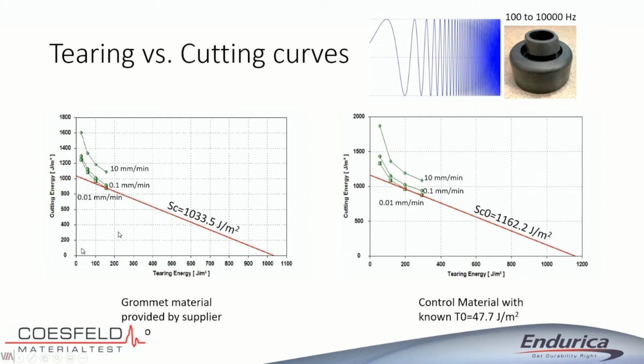Now, what you're looking at is a plot that has two axes. The x-axis is the tearing energy that acts on the crack that is due to straining of the material. So we're using a planar tension specimen. If you're familiar with crack growth measurements, same type of specimen. And the tearing energy is just the product of the strain energy density times the height of the specimen, just like it would be for a traditional crack growth test. So that's what you see on the x-axis.